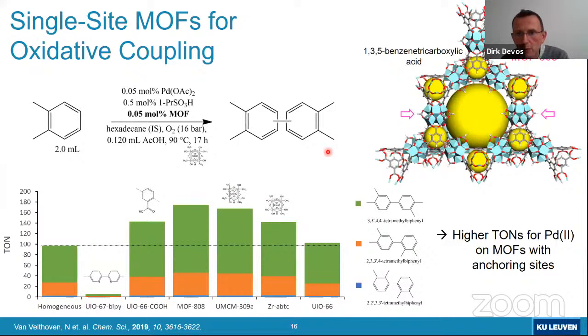Now, what is MOF-808? You could think this is an exotic material. Well, that's actually not true. MOF-808 simply contains these hexanuclear zirconium clusters linked together by benzene tricarboxylic acid, or trimesic acid, which is one of the simplest linkers that you could imagine in MOF chemistry. For instance, the very well-known copper BTC MOF also contains this precise linker, benzene tricarboxylic acid. And much will be made of this position on the cluster.